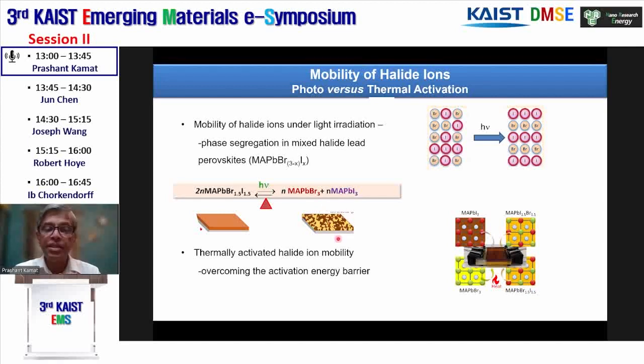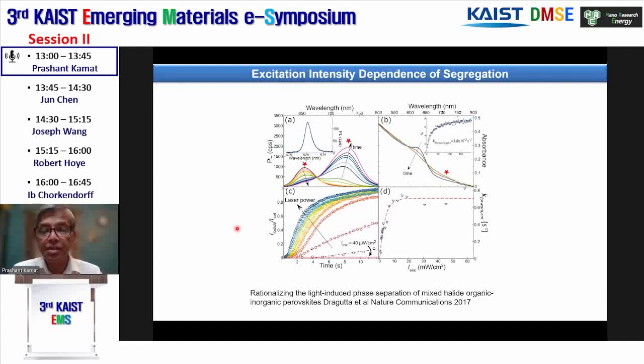And that's why you get these domains of bromide-rich and iodide-rich domains. But when you turn off the light, they will revert back to the original mixed halide composition. So in light, they want to be separate. In the dark, they want to be together. So that is the summary. And now we will see how we can monitor this.